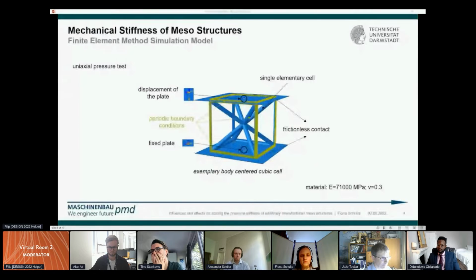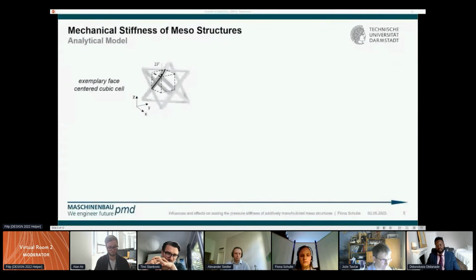To take the interaction of cells within a mesostructure compound into account, periodic boundary conditions are applied. These boundary conditions set the displacement of opposite nodes within the FEM mesh to be the same, like the elementary cell borders to another identical cell. The FEM simulations do output the overall stiffness, but provide little information about the contribution to the stiffness of the different geometrical features within the elementary cell. Thus, an analytical model for the pressure stiffness is derived from known mechanical interrelations and their description, supplemented with expected effects of the elementary cell's geometry.